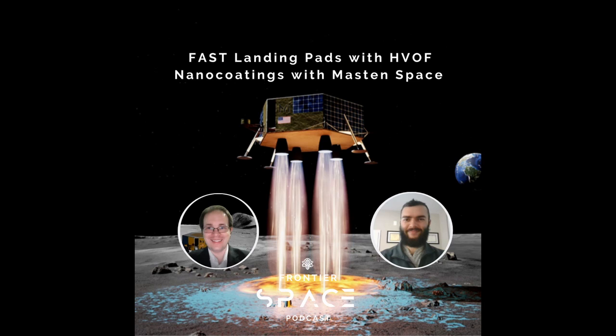So we're really changing up the game, and we're also deploying it directly onto the lunar surface, which is never really done here on Earth. It's always sprayed onto very prepared, usually metallic or ceramic surfaces. So you get really good particle adhesion, and you get really well-defined interface properties between the ceramics and the base material. Can't do that on the moon because it's an unconsolidated regolith.